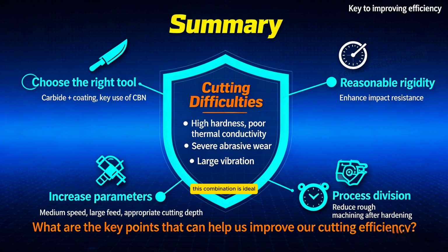This combination is ideal. Third, enhance the rigidity of the machine tool and work holding fixtures. Ensure adequate cooling, and optimize the machining sequence. Whenever possible, perform more rough machining before heat treatment to reduce the machining allowance required after heat treatment. Achieving these 3 points will significantly improve machining efficiency and tool life.